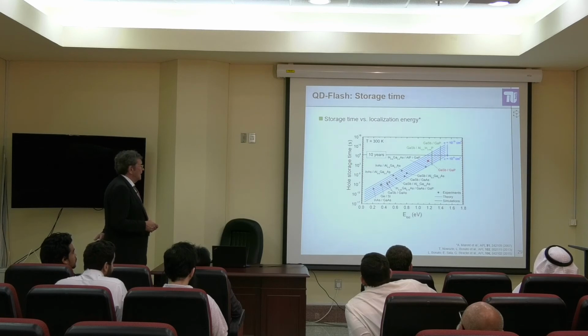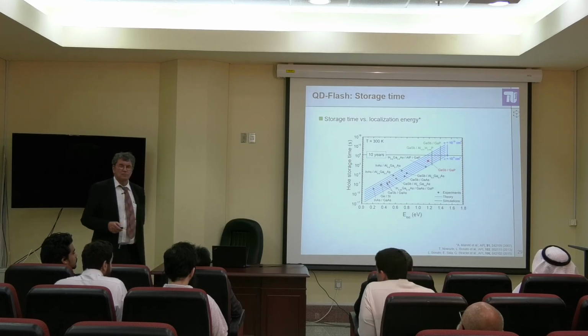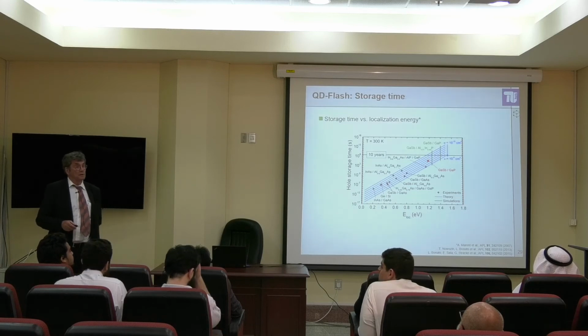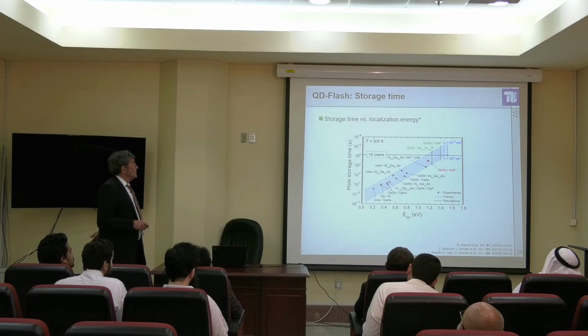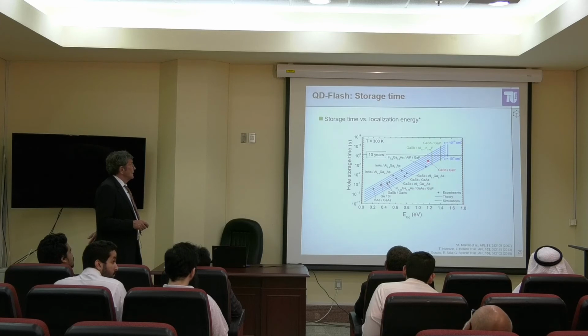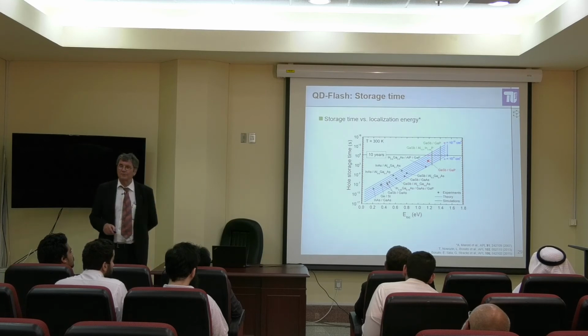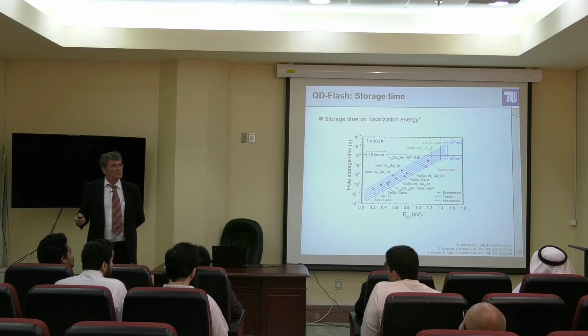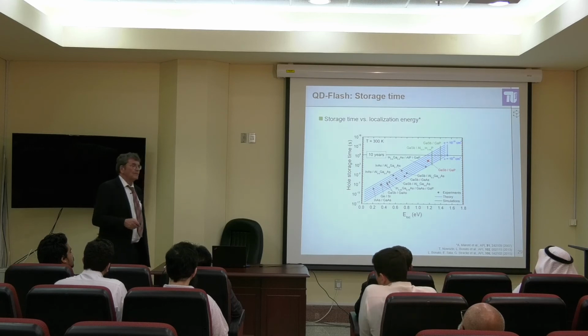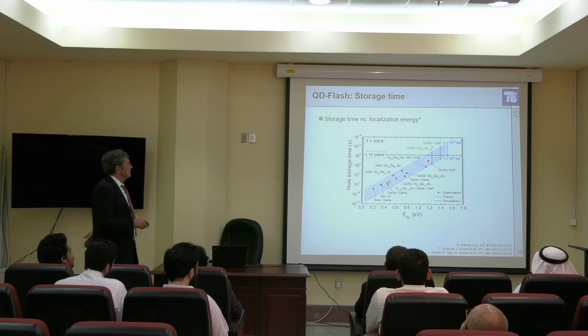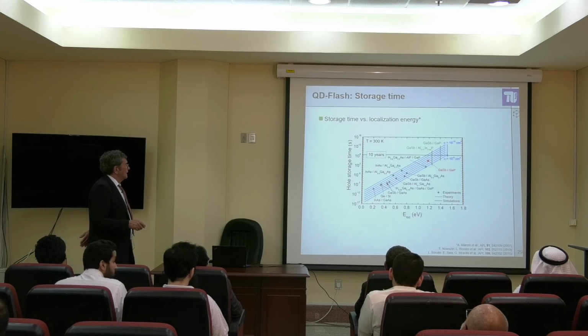Right now, we're working on a material system which was never done before. We were the first to make it. We have gallium antimonide quantum dots embedded in gallium phosphide. That is here, and we measured also the capture cross-section, which is here at that point. If it would be 10 to the minus 15, we would be at 10 years. Nature told us, the experiment told us, we are just in the middle of these lines here. We are at 10 to the minus 12. Now, next step.